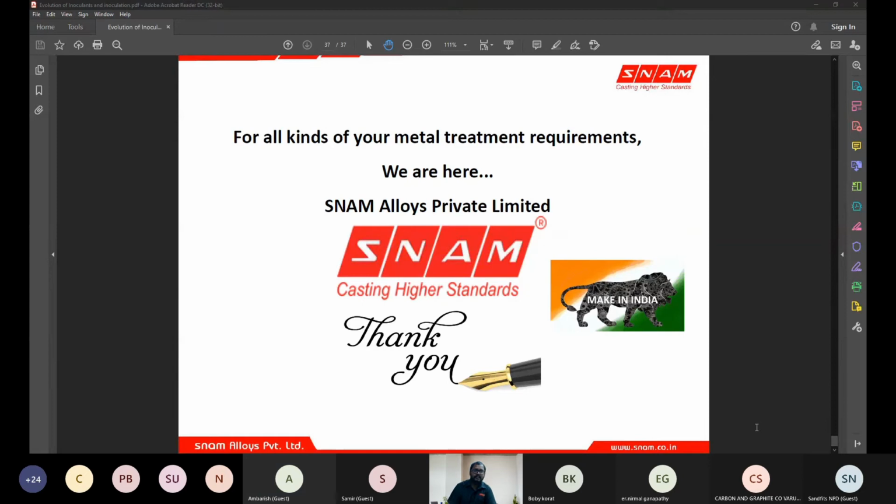And people even in India do in-mold inoculation, where they have seen good effectiveness, and your loss comes down. So in-mold inoculation also helps you get the maximum benefit. So for gray cast iron, generally people go lowest of 0.12, maximum 0.25, and ductile iron will be minimum 0.3, sir, because you have magnesium treatment there, so you need more inoculation. Okay. Thank you, sir.